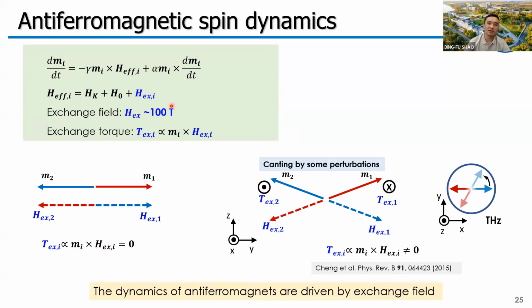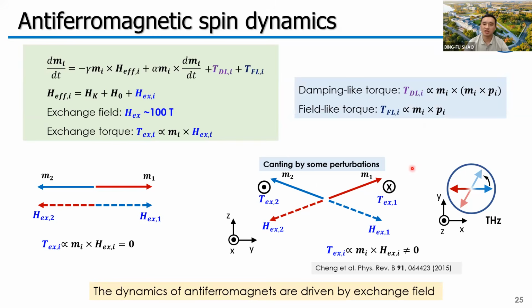Since in antiferromagnets the exchange field is usually very large, this staggered exchange torque can drive the ultrafast rotation of the two moments. Obviously, in order to realize the switching of the Néel vector, we need to find a method to generate such canting. In principle, we can use STT to generate this canting. However, in the antiferromagnetic tunnel junction we considered, we have only the spin neutral current where the spin polarization P is zero. So it seems we cannot generate such STT.